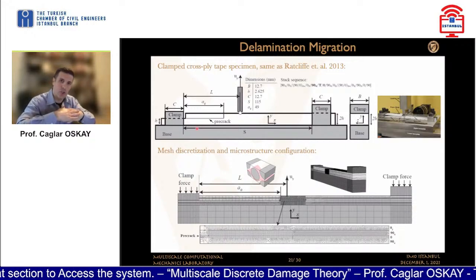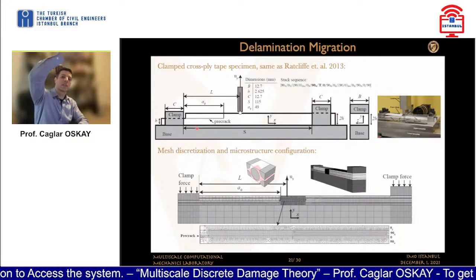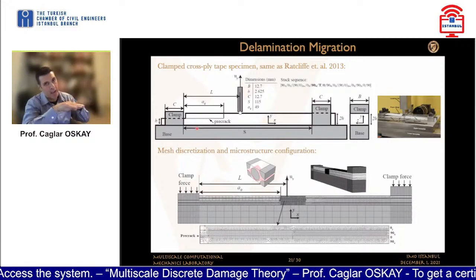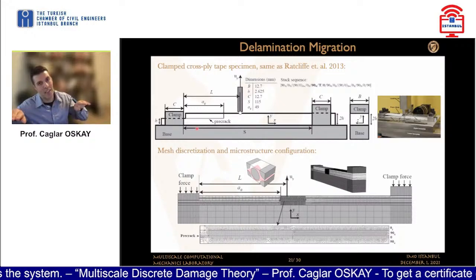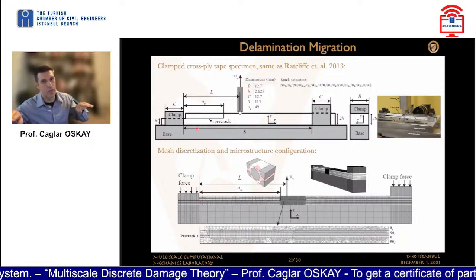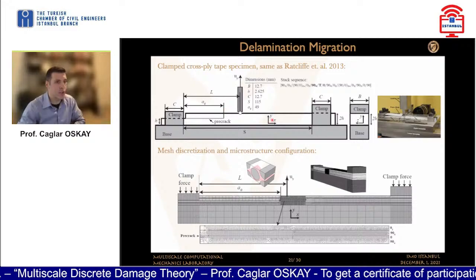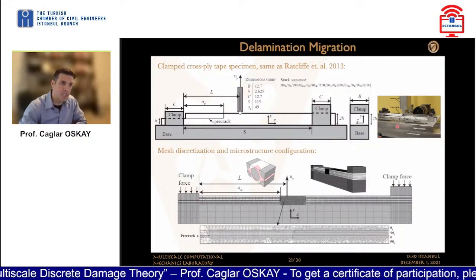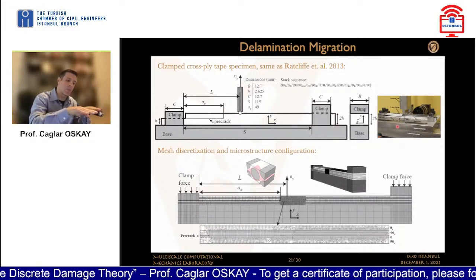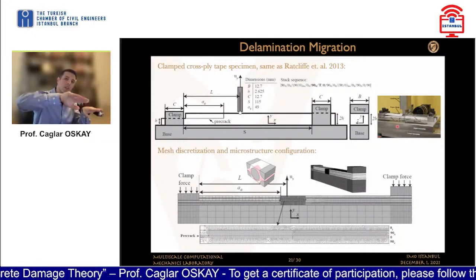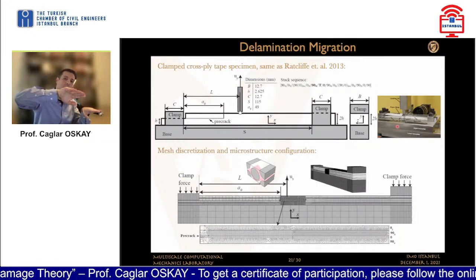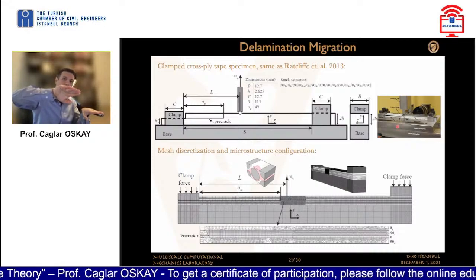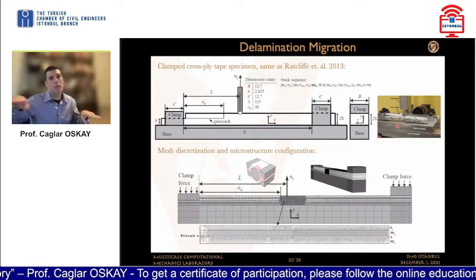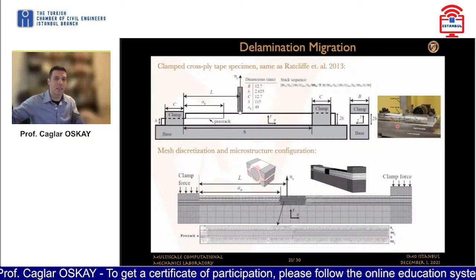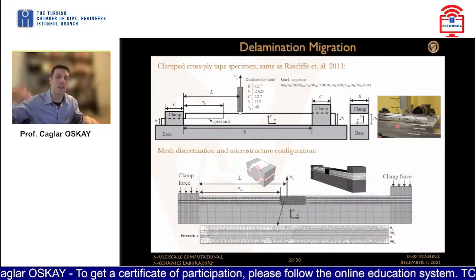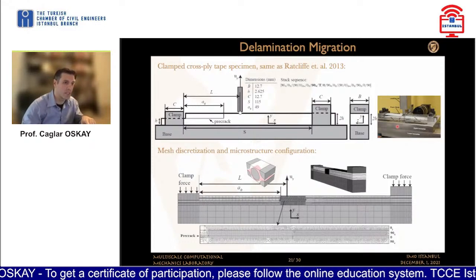And the expectation is that once you start loading it in more or less mode 1 direction, the crack is going to propagate horizontally through that interface. What happens, though, is a little bit different. What you see is that the crack propagates a little bit, turns, goes into the 90-degree layer, hits the 0-degree layer up top, turns again, and propagates in the interface that is a little bit above where it started.